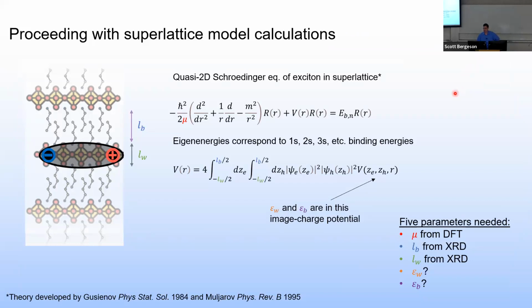I will skip over the math here and just mention that in order to make calculations within this model, which was developed in the 80s and 90s, there are basically 5 parameters that you need. You need something called the exciton effective mass, which relates to the effective mass of the electron and the effective mass of the hole. You need the length of the barrier, the length of the well, and also these dielectric constants. We could get the effective mass from density functional theory, which we have some collaborators that do that type of theory, and we could measure X-ray diffraction and get the structure of the material, which gives us the width of the well and the barrier. But we run up against some issues trying to figure out the dielectric constants to use in this model.